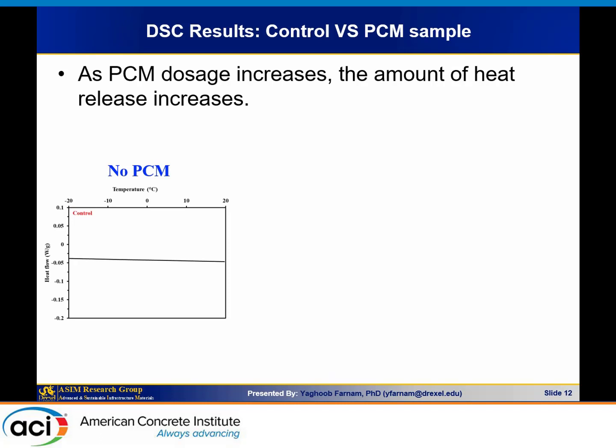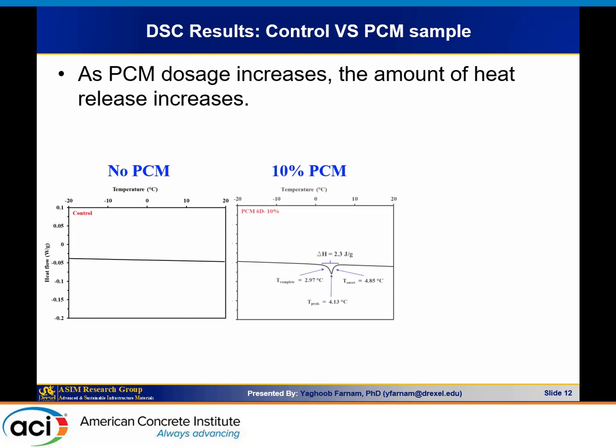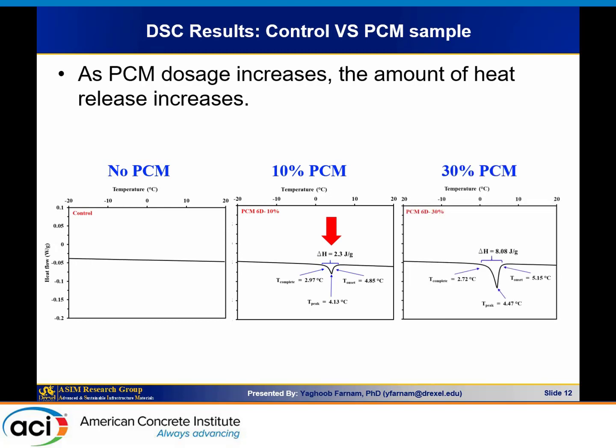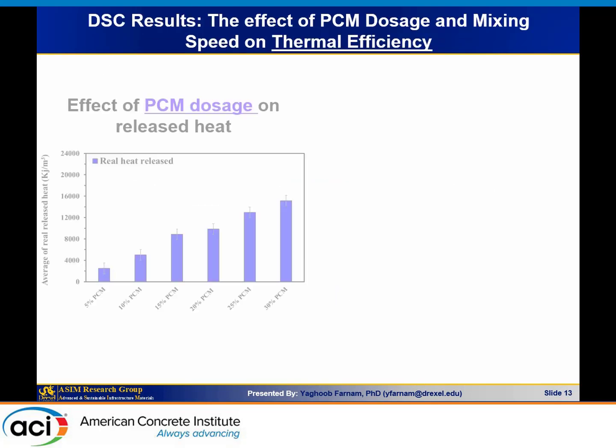If you look at the differential scanning calorimetry result, again, this is heat flow as a function of temperature. With no PCM, there's no spike, no peak. So it's what we expected. If we add 10%, we're going to have a little bit of a spike here, or a peak, and that is the heat release. If we add 30%, that peak is going to increase. And this is something that we expected. So what we could do is integrate that peak and find out the amount of latent heat inside that sample.